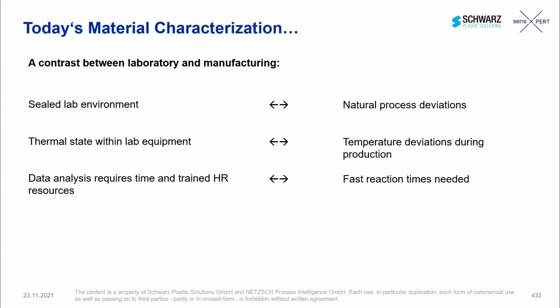Therefore, we vary temperatures in a simulation environment, and also humidity, to create a huge amount of data sets to see the dependency within different states of the environment. We have a very long bridge to gap between the laboratory environment and the process environment, because the laboratory environment is nothing like the process environment. We have temperature deviations within the process environment we will never see in an isolated environment during a lab characterization. And we have material deviations we cannot really follow, batch-to-batch deviations that occur during the manufacturing process. We have to react to them. And that is what we do.